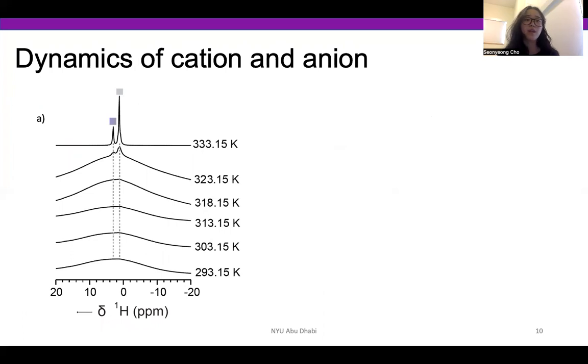And finally, the dynamics of the cation and anion was studied by using solid state NMR. So panel A shows the results obtained from proton solid state NMR without magic angle spinning. So you can see that at lower temperature, 293.15 Kelvin, the spectrum is very broad and featureless due to anisotropic NMR interactions and lack of motional averaging. But as you can see, with increasing temperature, the peaks gradually narrow, and the appearance of a well-resolved peak around 1.3 and 3 ppm indicates the presence of dynamics, which can average the anisotropic NMR interactions.